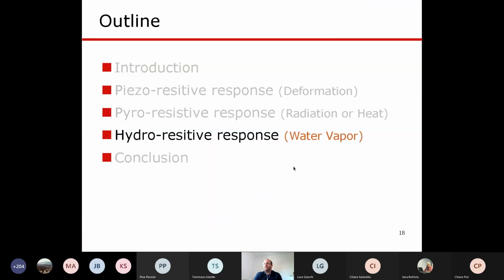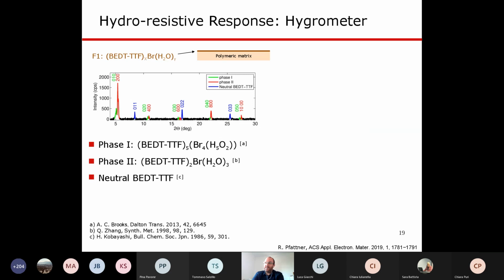Now, this brings me already to the last example of sensors or films that we use to prepare, in this case, humidity sensors. Again, similar as before, we used a polymeric matrix, and on top we grow this crystalline layer that is actually sensitive to the humidity. Now, when we analyze this, we get this picture over here, which shows an XRD spectrum. And that's something interesting because in this case, scientists can use XRD, which is a very short wavelength, to measure the distance between the molecules. And interestingly, when we measured the signature of our sample, we saw different peaks, different groups of peaks, green, red, and blue, and we could actually analyze them.